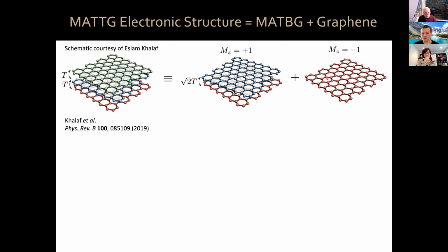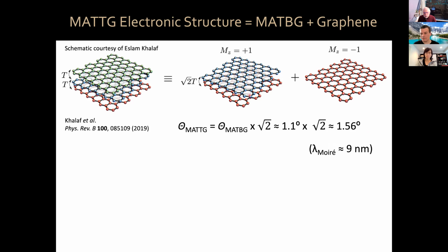Now, because of this square root of 2, remember, I told you earlier that the interlayer tunneling determines what the magic angle is. So because we have a square root of 2 here, the magic angle for magic angle twisted trilayer graphene is the one for the bilayer times square root of 2. So it's 1.1 times square root of 2, 1.56 degrees. And this means, by the way, that the Moiré wavelength, which I told you for magic angle bilayer was 13 nanometers, because now the twist angle is a bit larger, the Moiré wavelength is smaller. It's about 9 nanometers for this system.